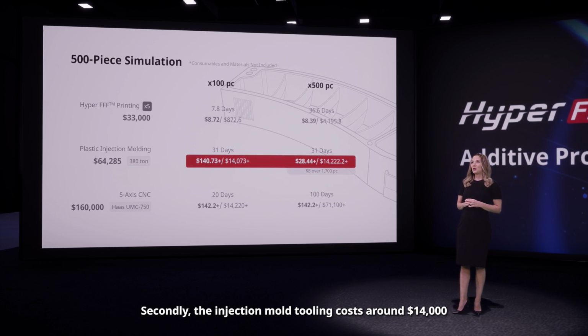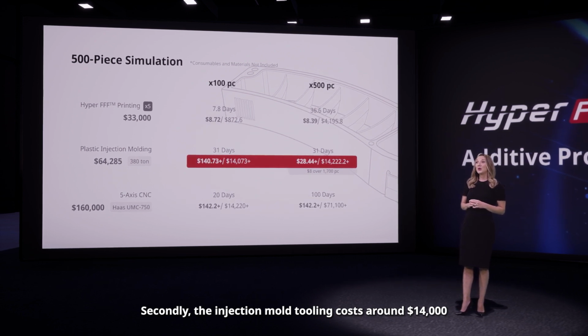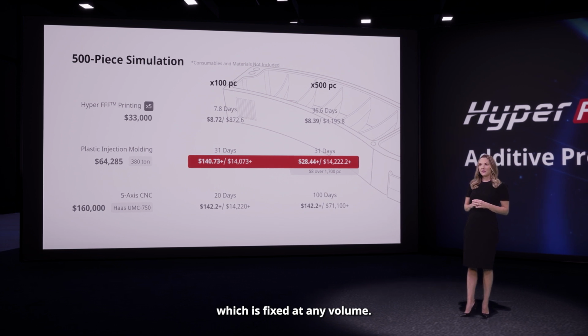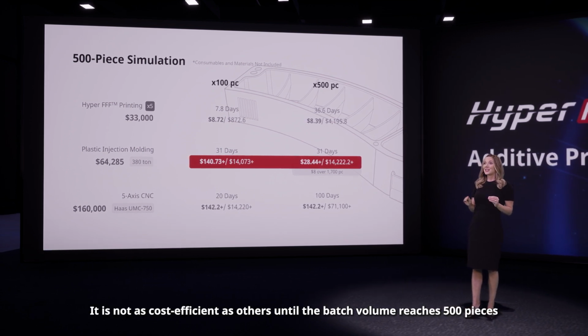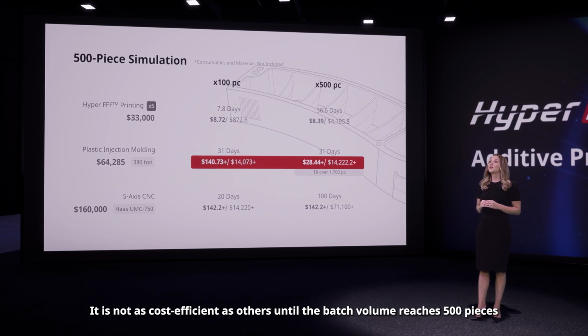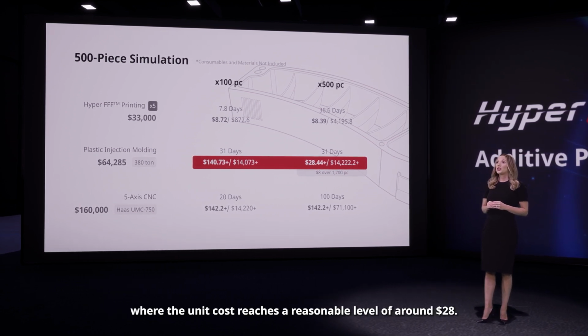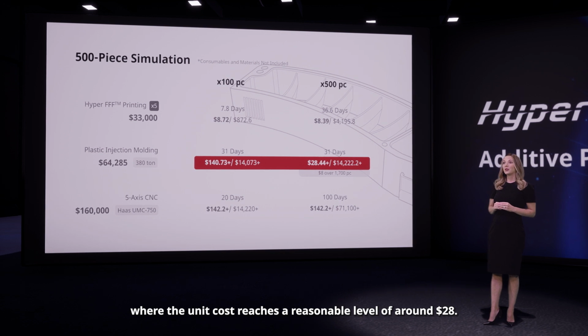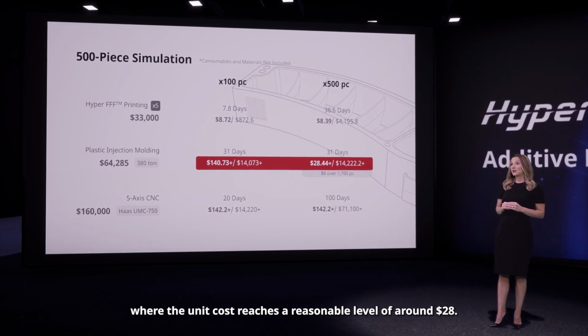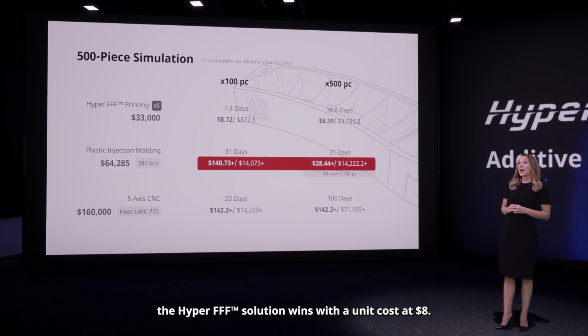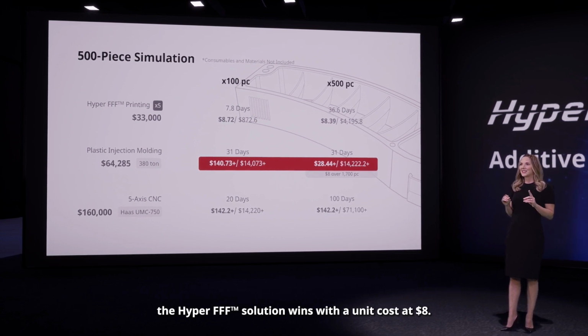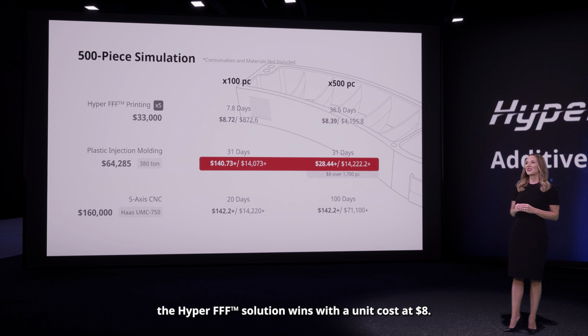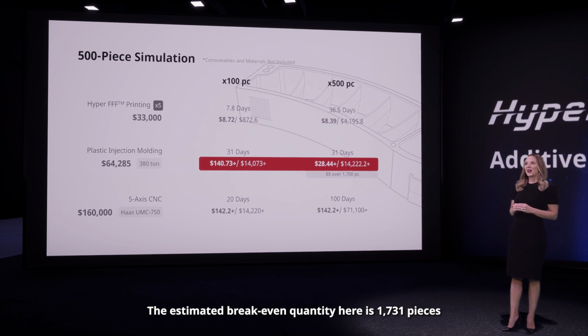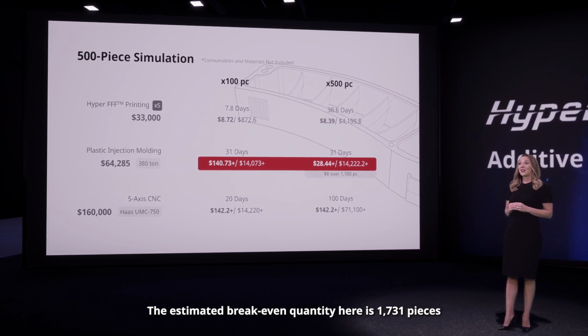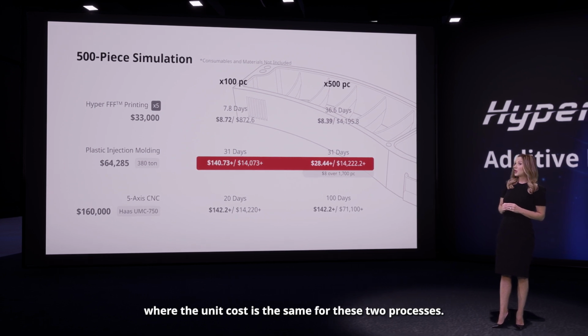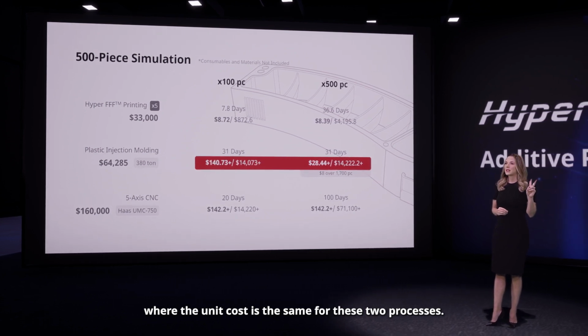Secondly, the injection mold tooling costs around $14,000, which is fixed at any volume. It is not as cost efficient as others until the batch volume reaches 500 pieces, where the unit cost reaches a reasonable level of around $28. However, in this scale, the Hyper FFF solution wins with a unit cost of $8. The estimated break-even quantity here is 1,731 pieces, where the unit cost is the same for these 2 processes.